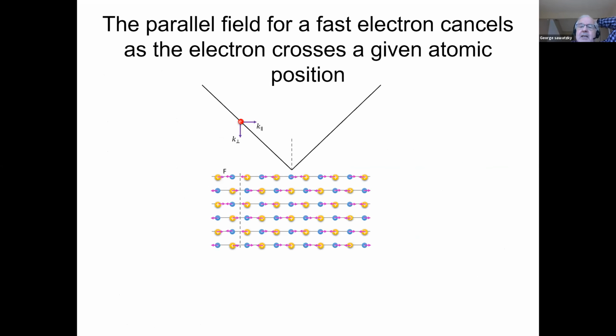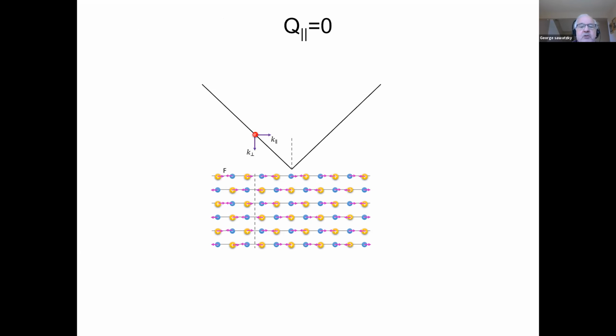And this is a Q equals 0. It's a longitudinal optical phonon that is polarized perpendicular to the surface. So if I just look at a material and have an electron coming in at fairly high speed, coming in like this, then as it crosses, its electric field, of course, in the perpendicular direction would be pointing in that direction, but there's a horizontal field, and it is oscillating, it is pulling that atom to the left here, and when it passes it, it'll pull it to the right. And that, because it's going fast, it averages out because the atom doesn't have time to move that quickly. Okay, that's seen here. The arrows change, right?